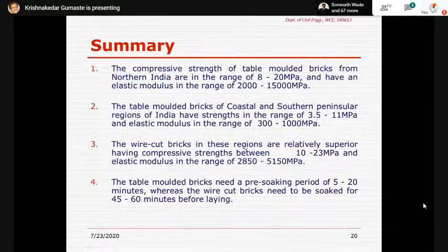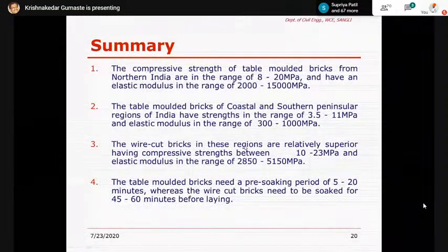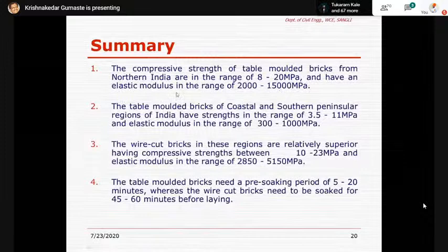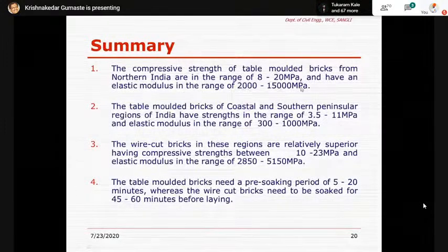So that is the first part which I wanted to get into, where I would summarize that the compressive strengths of table molded bricks from North India are in the range of 8 to 20 megapascals and have an elastic modulus in the range of 2000 to 15,000 megapascals in general, inclusive of table molded and wire-cut bricks.